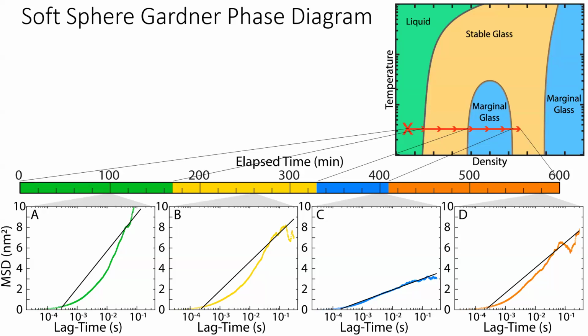It also is frustrating because a very obvious question is, well, why didn't you just wait longer and then go into the high density marginal glass phase? And it's because these measurements are very, very vibration sensitive, right? Because we're looking at the thermal breaking of these marginal structures. So they're by definition very, very weak. And so in the morning at about 6 a.m., when people come in to clean, that's the end of the measurements. We can't do anything more.